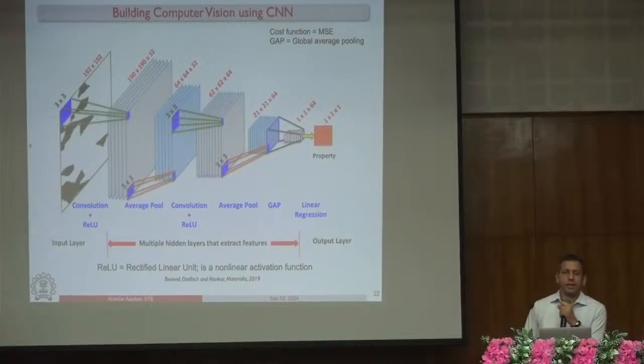of elasticity, right? Modulus of elasticity, if you just talk about an elastic material, is nothing but the stress at a given strain. If you fix that strain, that is modulus of elasticity, right? If you do not use this nonlinear function, you can never capture nonlinearity, right? This problem is rather very simple because there are only two phases, and we are deforming the material very close to yield point. There is a very low amount of nonlinearity which comes because of plasticity, and ReLU was able to capture it. ReLU, you may be aware, is nothing but it just takes the positive x when you pass it any x, it drops the negative x, right?